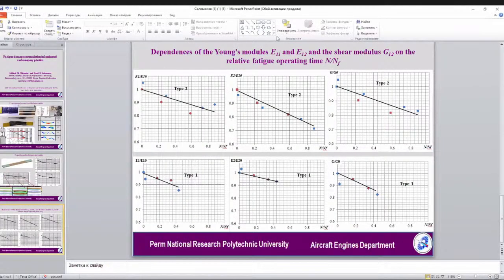Thank you for your presentation. I have one question regarding the fatigue testing that you performed. You mentioned that you have used 40 hertz as the frequency for fatigue loading, and that it didn't cause any raise in the temperature. We saw an increase in the temperature of the samples during the testing, not in all types of samples. Sometimes we use special equipment to cool the sample with air during the testing.